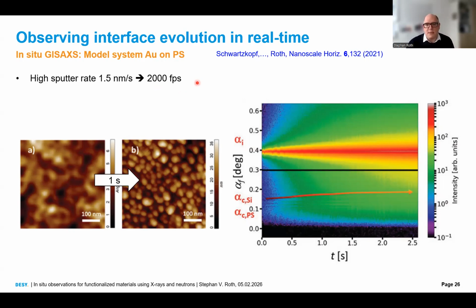This means that if you run this continuously, you can imagine how many gigabytes you would produce. And what we then typically do is we make these maps. This is the time or deposited gold thickness. This is the exit angle, alpha f, and color-coded is the intensity. So we plot here the vertical cuts. And then you see here fringes, and these fringes move. Remember what I said? These fringes have to do with the layer thickness, and the maxima have to do with the Yoneda peak. And the Yoneda peak is proportional to the square root of the density. So something is happening here where the density changes.